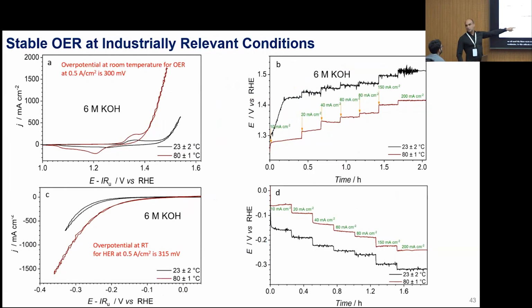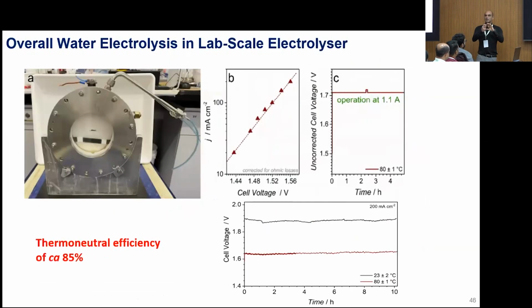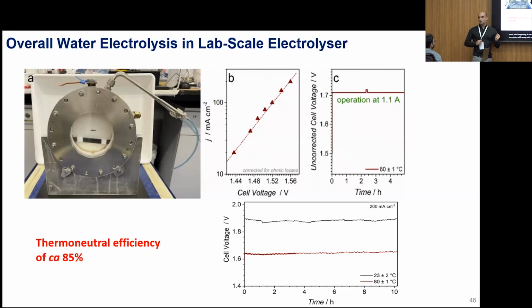Also for the HER reaction, very similar story. Right? So we went into integrating it into a small electrolyzer, and we were able to produce hydrogen with 85% thermoneutral efficiency with something based on iron, which is $100 per ton, and phosphide, which is about $300, $400 per ton. So actually, very proud of this result.